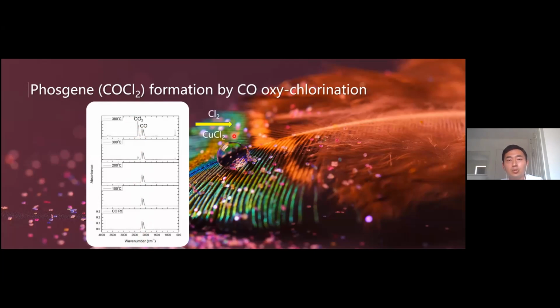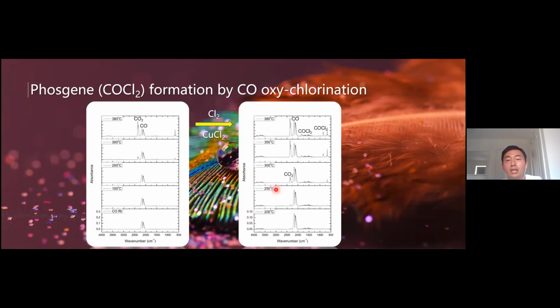So what should I do then? Because CO oxy-chlorination requires chlorine as a resource, by pre-treating the catalyst with a small amount of dichlorine, we can activate the catalyst. Then when the mixed gas flow of CO and HCl passed through the catalyst, we could see that besides CO2 formation, which was attenuated, we could see phosgene formation finally.